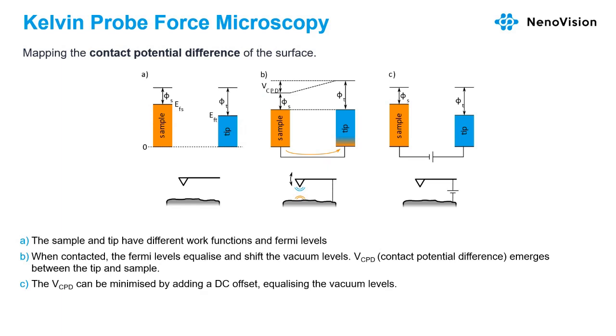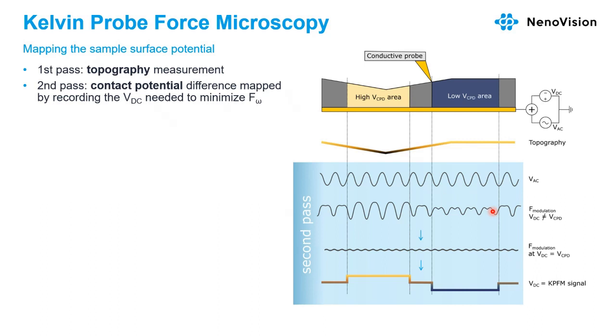Measuring the surface potential is a bit more complicated, so I have a bit longer description here. There are three possibilities in the setup of what can happen. So we have the sample and tip, which are not in contact, so they have different work functions and different Fermi levels. Now, when they get into contact, the Fermi levels equalize but shift the vacuum levels, and so there is a contact potential difference which emerges between the tip and the sample. And so what we want to do is minimize this contact potential difference by adding some voltage, equalizing the vacuum levels. So that's exactly how we measure Kelvin probe force microscopy.